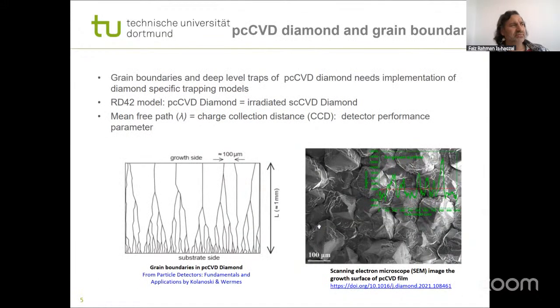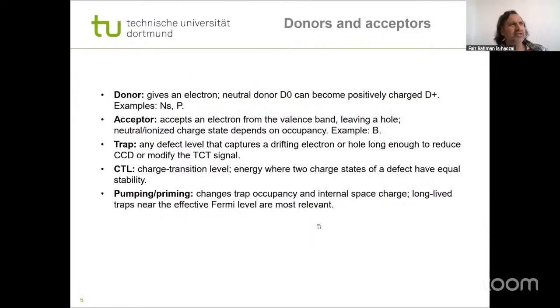In PCCVD diamond, you can see the grain boundaries, which are a big problem because they trap the electrons or holes which are drifting across the diamond. It traps them there and we lose the signal. It's very important for us to characterize the effect of these grain boundaries in the detectors, and it's one of the main problems that I and our group are working on.